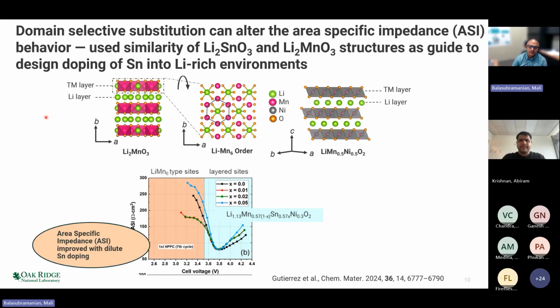The other point that I had made was that XAFS is very sensitive to dilute dopants or impurities, and so it can be a very useful probe to see the effect of dopants in systems. And here the example I'm going to show is a study of tin dopants in this complex lithium-rich manganese and nickel-based oxide.